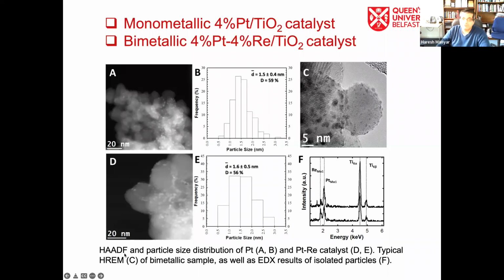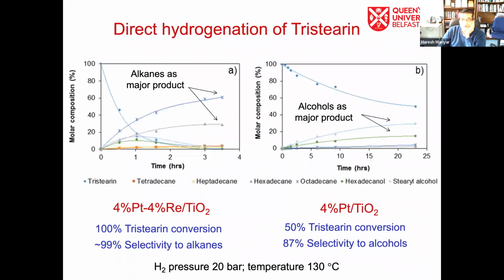So as you can see, we have prepared nice monometallic and bimetallic platinum, rhenium type of materials supported on titanium, and the particle size distribution is very narrow, in the range of 1 to 2 nanometers, very small nanoparticles. And we studied them for direct hydrogenation of tristearin as the model substrate for representing the triglyceride, for representing the oils. And by tuning between the monometallic and bimetallic catalyst, we can selectively achieve 100% conversion and very high selectivity either to hydrocarbons or to alcohols.